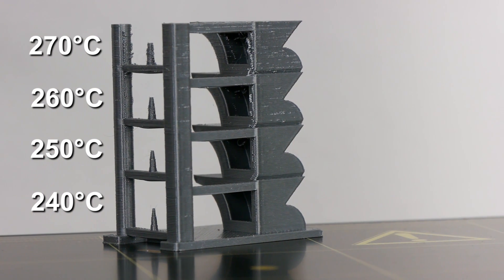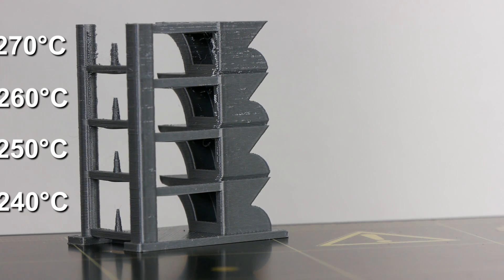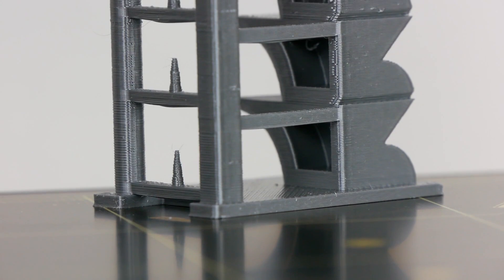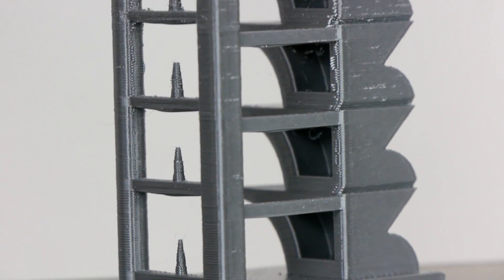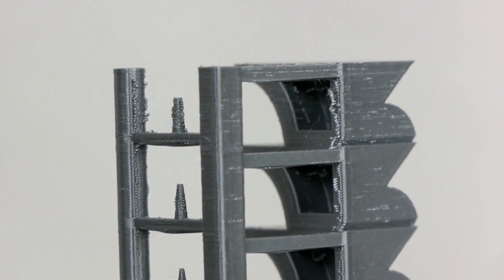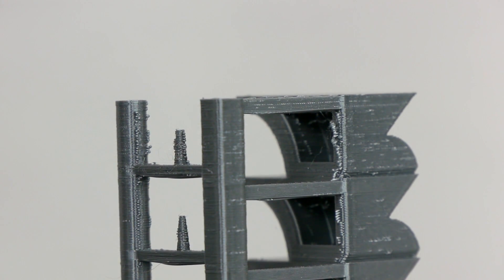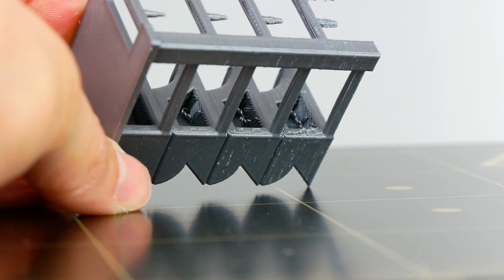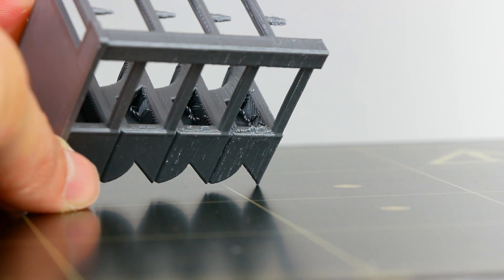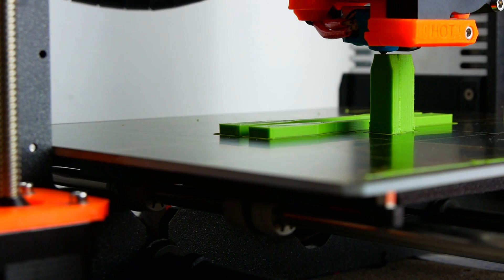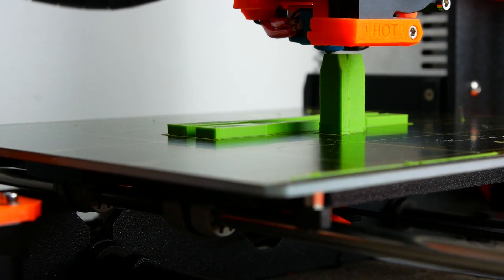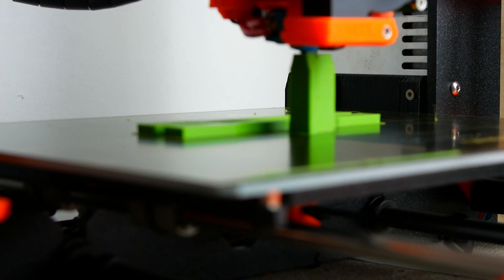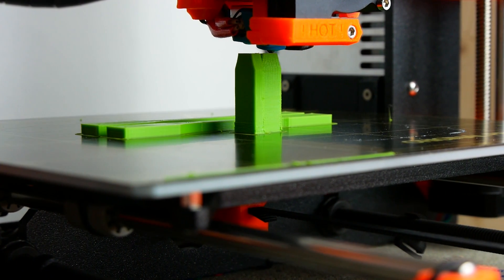My guess was that the higher print temperatures might be better for layer adhesion, so I wanted to know how far I can go. Just like before, 240 degrees Celsius was still fine, but starting at 250 degrees lots of bubbling started to show and small chunks of PLA appeared at the start and end points of the extrusions. The bubbling is probably due to moisture in the material. I have to say that I opened this material 5 months ago. Using brand new or dried material might enable you to print PLA at these temperatures, but realistically I guess 240 degrees should be the maximum. Also it started to smell quite a bit at these temperatures.